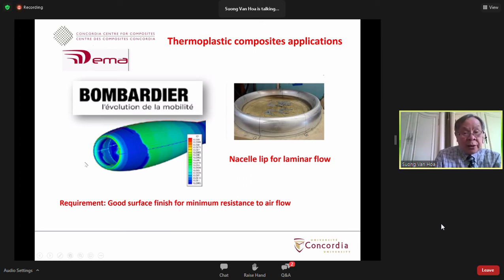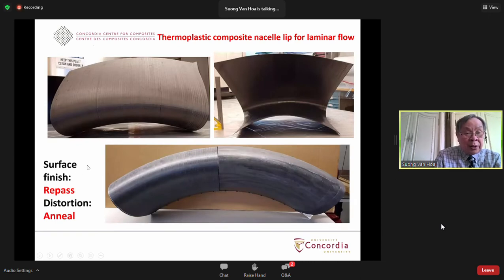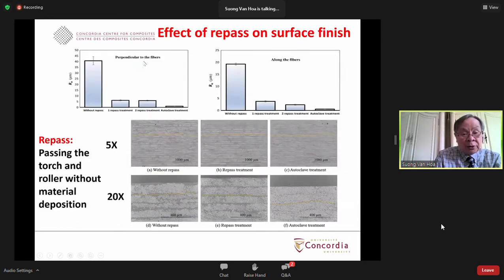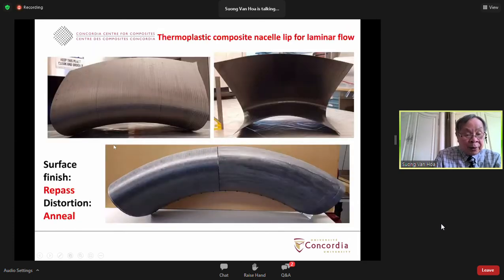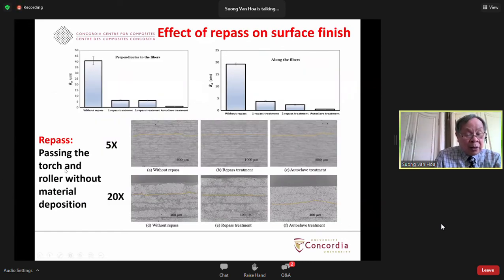So in this case, that means we have made the pieces here, and you can see that the way we address the kind of finish is by using a technique called repass. Repass means that when you finish it, you can run the machine over the surface without any deposition. The other aspect you have to address is distortion, and we have to use an annealing technique to address distortion. Repass means passing the torch and roller without material deposition.